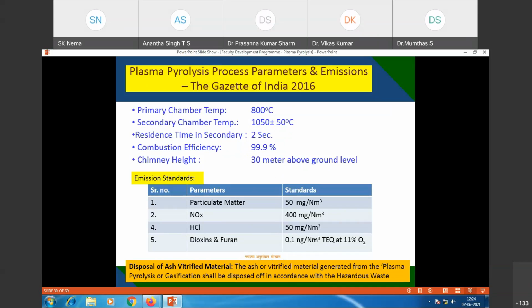And these are the standards for different gases. Your particulate matter should not be more than 50 milligram per meter cube. NOx should not be more than 400 milligram per meter cube. And similarly, HCl should be less than 50 milligram per meter cube. And to take care of the ash, it should be vitrified, or it should be dumped in a secured landfill.